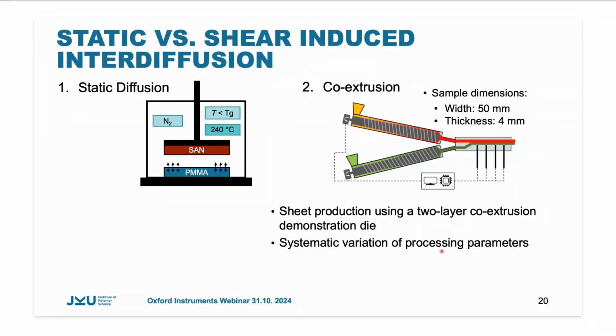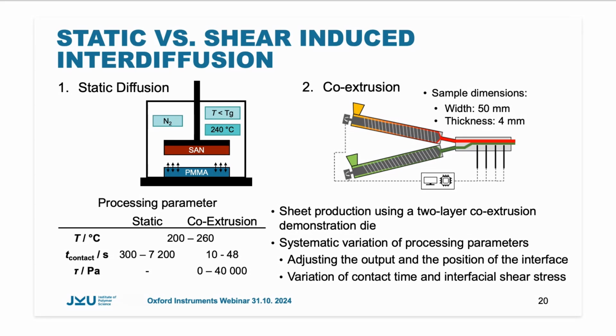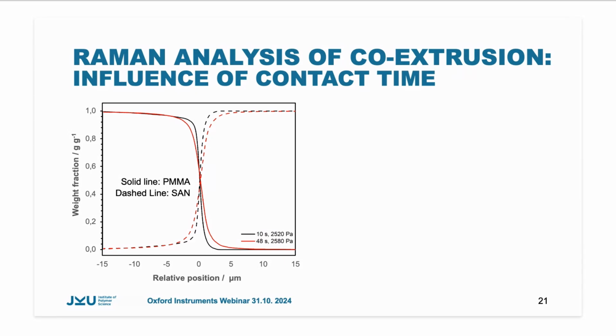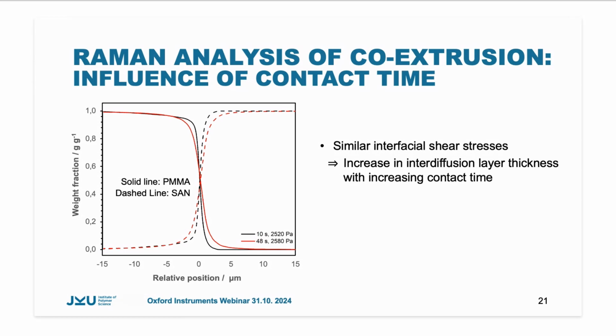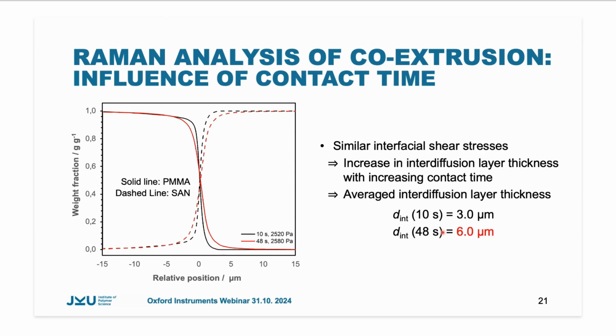We could systematically vary the processing conditions in a way that we adjust the output and the position of the interface, thus varying the contact time and the interfacial shear stress of the experiments. Our first goal was to study the influence of the contact time. Therefore, we prepare samples under similar interfacial shear stress. What we saw is that there is an increase in the interdiffusion layer thickness with increasing contact time. And the average interdiffusion layer thicknesses are 3 micron for contact time of 10 seconds and 48 seconds contact time leads to 6 microns interdiffusion layer thickness.